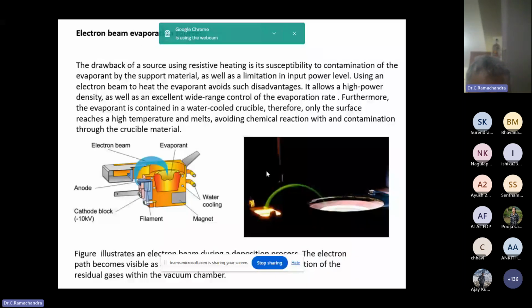To avoid that, we prefer electron beam, because now the electron beam is generated completely outside. It is magnetically energized and taken and it bombards the evaporant. So the temperature now is very less, therefore it works almost at room temperature. Because of the high energetic bombardment of the electron beam, these materials get evaporated. It is highly localized evaporation. So it is relatively cool, temperature is very less, and also there is no impurity concern from the sample holder. That is the advantage of electron beam evaporation. But the system will definitely be costlier compared to thermal evaporation.